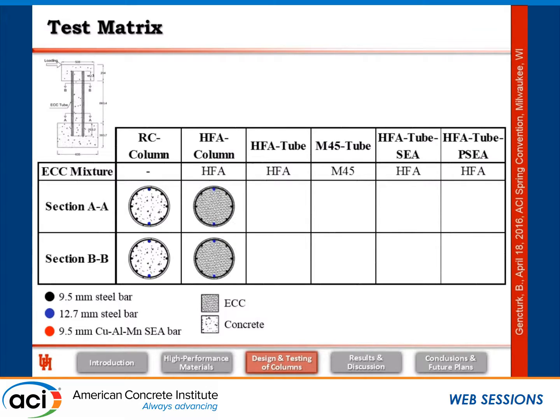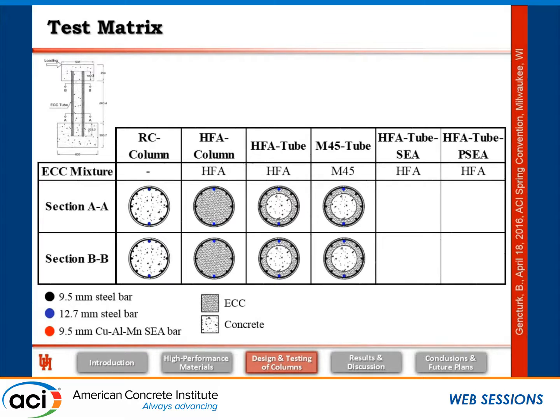And then in this case, this is very similar to a conventional column. The only difference is that instead of putting concrete, we put HFA, which is one type of the ECC we are looking at. And in this case, this is now the tube, but still has the steel reinforcement, so there's no super elastic alloys in this one. And then this one is the same as the previous one, but it uses a different ECC. Instead of using HFA mix, it uses M45 mix. HFA has high fly ash, that's why it's called HFA, and M45 has a little bit less fly ash.